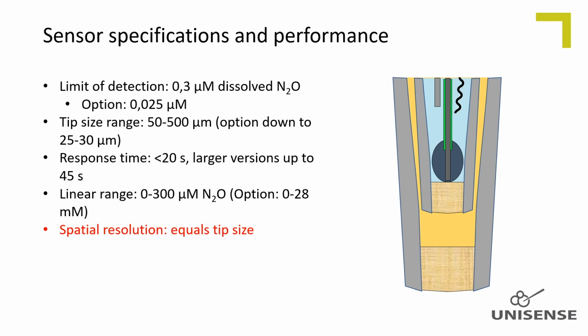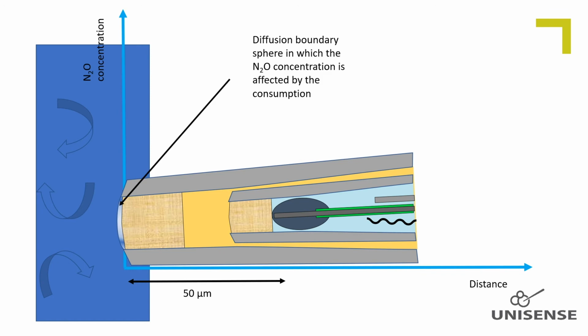The spatial resolution equals the tip diameter. This is just a rule of thumb because it cannot easily be validated. The sensor will sample nitrous oxide from a very minute diffusion sphere at the membrane/sample interface. But when profiling in biologically active matrices, physical disturbances should also be considered, which increase with tip size.